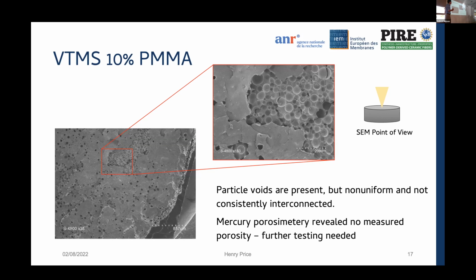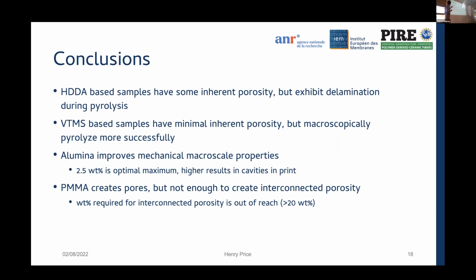So the conclusions from my work. First on the resin chemistry, those with HDDA cross-linking agent have some inherent porosity, as you saw, but generally on a macro scale have much more delamination, mechanical failure. The VTMS samples, they have less inherent porosity. However, on a macro scale, they are more successful after pyrolysis.